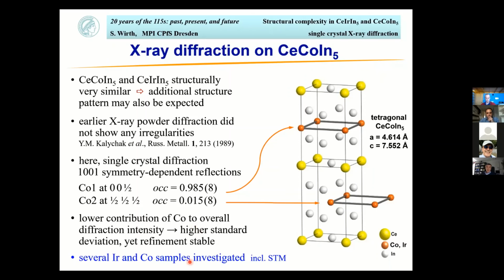I should point out here that we have investigated a few samples. I think it was 5 iridium samples, several cobalt samples, including the one I will talk about in a moment, which we used for STM. But let me make that clear here: in principle, we would have to do that for each and every sample. I also don't want to claim that these samples are bad in any sense. These are really high quality samples. You just don't see it with a regular X-ray diffraction experiment because you have such a very similar pattern. These are the same atoms, just slightly displaced in the iridium or cobalt case.